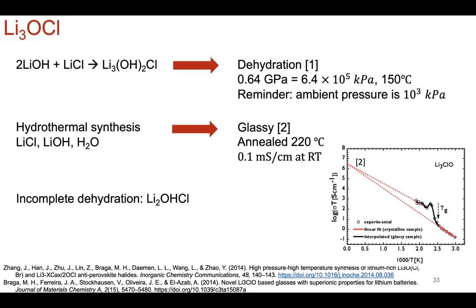Correct. But that's difficult to track down, because when you do the characterization, you don't always pick up the tiny amounts based on what's already out there. The reports that are out there. It's not obvious what the percentage is, based on how someone reports their methodology. So in terms of processing and fabrication, it's extremely challenging to pinpoint and say, this is really the value for Li3OCl, because it's not clear from the literature how much of this hydrated phase is actually in there. So that's the key issue for these types of compounds currently.